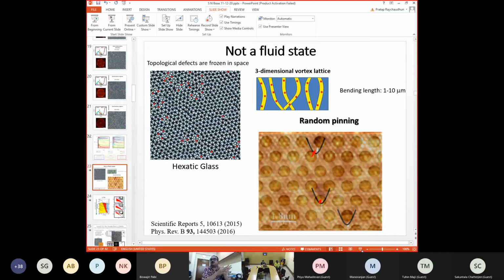We took crystals which were 50 to 100 micron. This particular experiment was on a 50 micron crystal. And therefore, it's not even two-dimensional, and we should not expect really a Kosterlitz-Thouless transition. Then why are we seeing this hexatic glass? That also we figured out, and that is actually because of pinning.